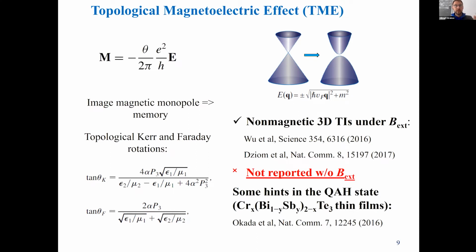How do you do that? First, you should induce the Dirac point gap, as I explained previously. Then you place the Fermi level exactly here in this gap. And then at a certain thickness, which for bismuth telluride type topological insulators is about 20 nanometers, as far as I remember, you can be in the quantized regime. So the film thickness should not be too thin, let's say.